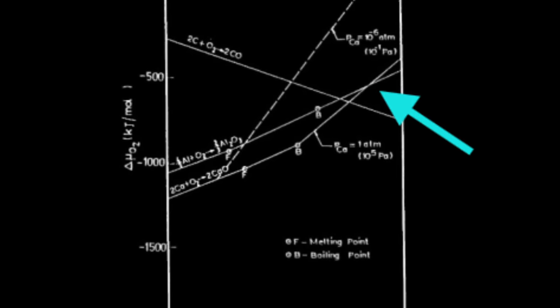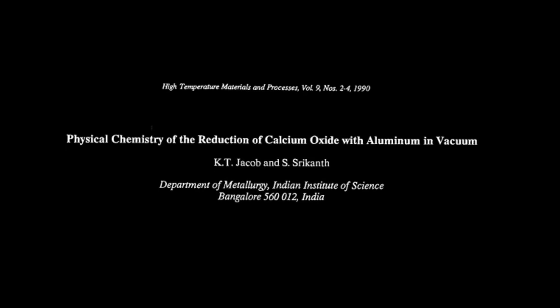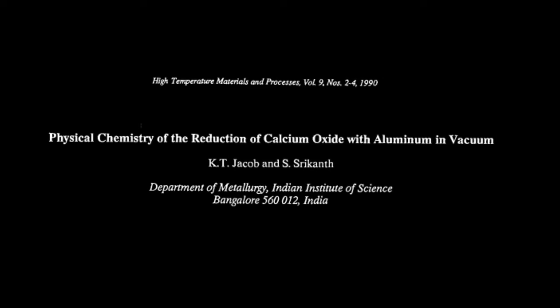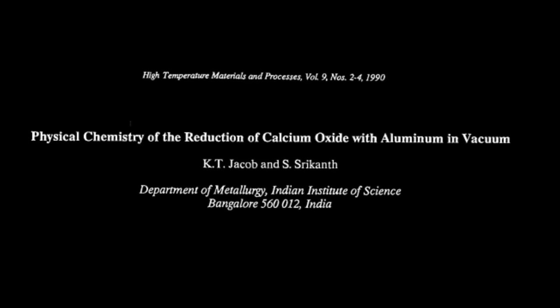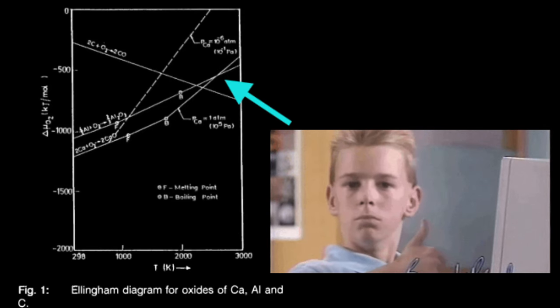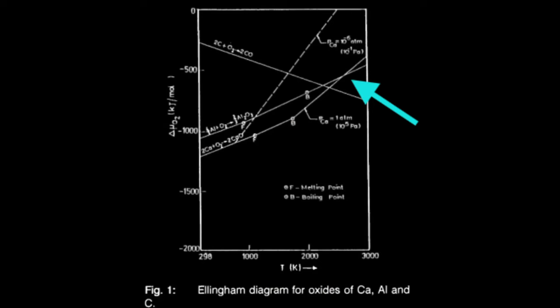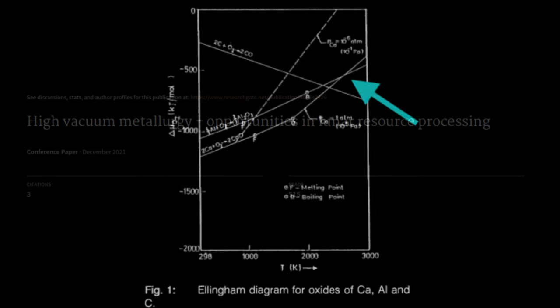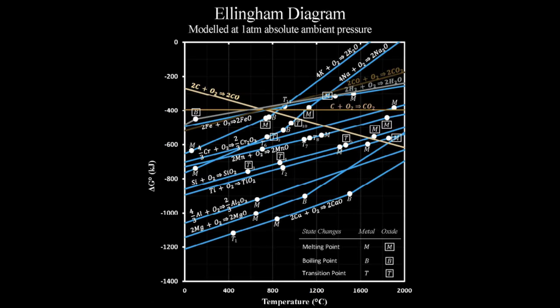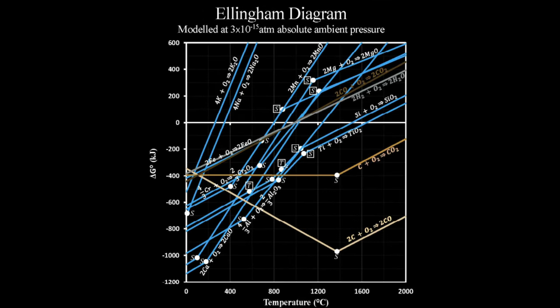However, this paper was not about the crossover itself. It was about the fact that this crossover happens at much lower temperatures when in a vacuum. At first, this didn't really stand out to me as anything more than a neat little trick. I knew that the melting and boiling points of substances were lowered in a vacuum, so it wasn't surprising, but the Ellingham diagram and the paper only showed calcium and aluminum, so I wanted to see if I could find any diagram showing all the elements in a vacuum, just out of curiosity. And I found this paper, which presents a set of Ellingham diagrams at different levels of lunar vacuum.